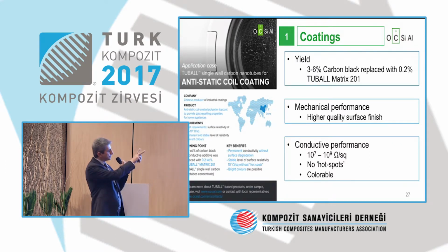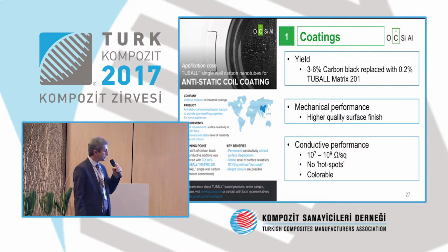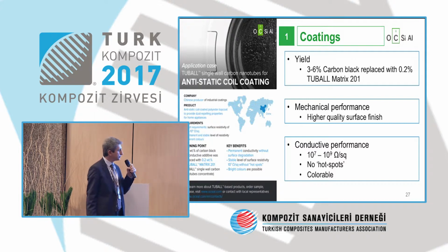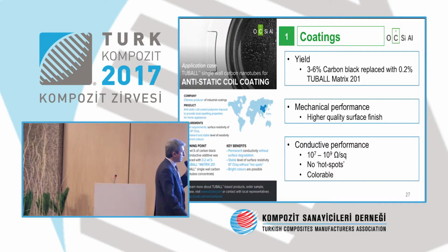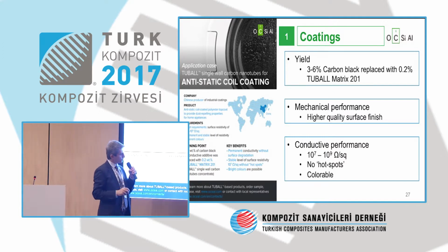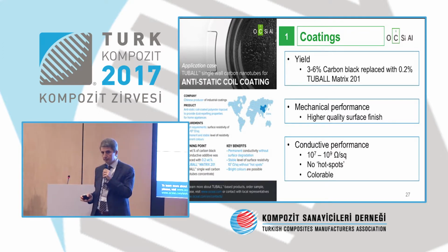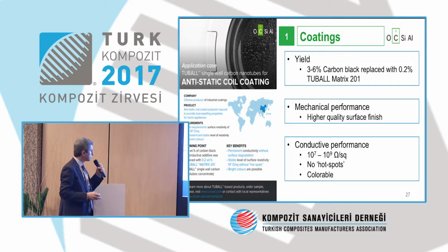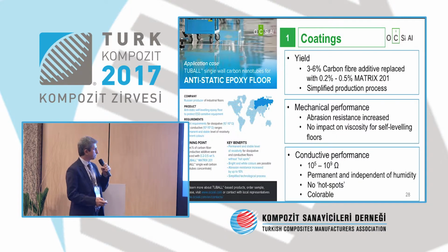Antistatic coil coating, by the way, taking a look at the yield, the 6 to 3% of carbon black was replaced with 0.2% tubular matrix 201, and through that the material has a good conductive performance of 10^7 to 10^9. This producer is a coating company in China, but it has also been approved in the United States, not only in Asia.